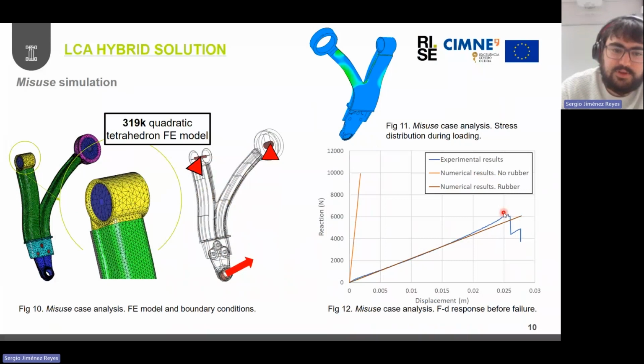As Matthias mentioned, we could not really go into fatigue experiments just because in the misuse scenario where we apply the monotonic load, we get this detachment between the aluminum layers in the demonstrator. But at least from the numerical perspective, we were able to reproduce this monotonic response. And this is the comparison between the numerical and the experimental responses that we obtain for this demonstrator. And what we observe here is that the numerical model also captures this stress concentration in this edge region of the lower control arm here, meaning that we can also identify this potential problematic area in the connection between the two aluminum layers.